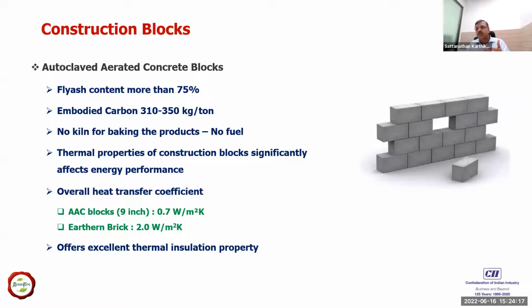During the mixing itself, there is an aeration happening. The brick becomes very porous and lightweight, and then the moisture is removed. It can even be sun dried. So there is no need for putting this in a kiln to bake it. Because of this, the embodied carbon of these kinds of products is much lower compared to a conventional brick. It is only about 300 to 350 kg of CO2 per ton.